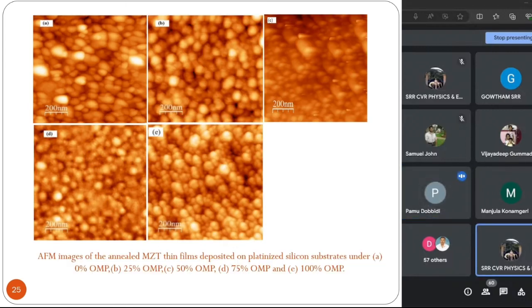You see that with respect to different oxygen partial pressures, we have shown you the micro AFM pictures. AFM is nothing but atomic force microscopy pictures, where you will be able to see at a nano level the beauty of arrangement of grains that are present in the sample. You see that the samples are purely in the nano scale, and they have a very good response. So can you go to the next slide, please?